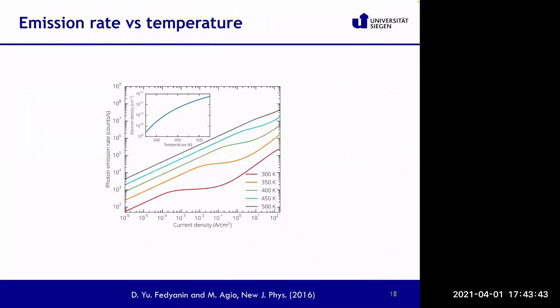we have to talk about the temperature. Temperature in diamond is very important, because if you increase the temperature, you are able to activate exponentially more and more electrons and holes. So by doing so, by increasing the temperature by just 50 or 100 degrees, you can have a considerable improvement in the emission rate, because you essentially provide more electron and holes. And here you see that the photon emission rate can really go up by many orders of magnitude if you increase the temperature by, let's say, 100 or 200 degrees. So eventually you can get to 10 to the 7, 10 to the 8 photons per second. And this is competitive to optical excitation.